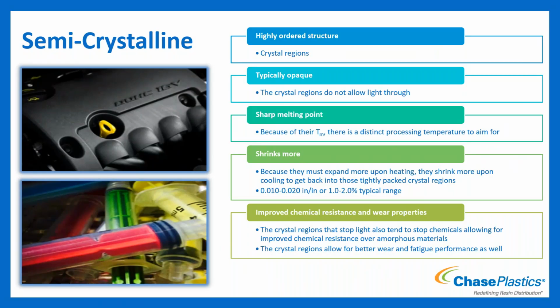They tend to shrink more. And so you'll see that across the board as I cover the materials, I also include a broad shrinkage range. It's typically going to be a wider range, and it's going to be a higher number, a larger value for shrinkage for your semi-crystalline materials compared to your amorphous. Okay, and then they tend to have improved chemical resistance or wear performance. You'll see in some of the materials that I cover, that's going to be some of those value propositions, that they have good chemical resistance or good wear performance. You'll see that pretty commonly with our semi-crystalline materials.